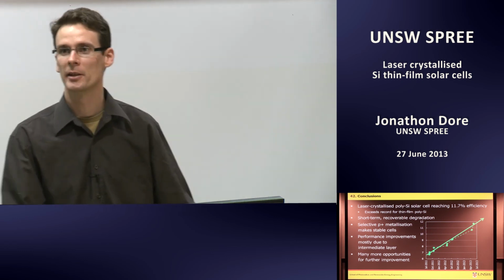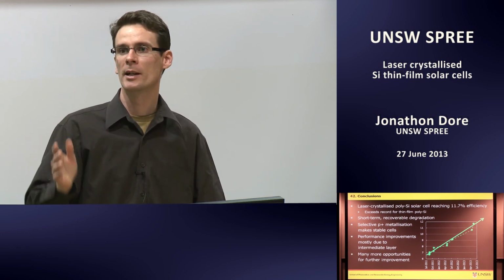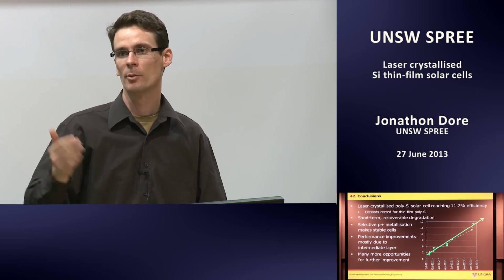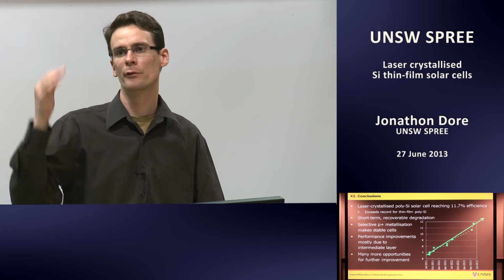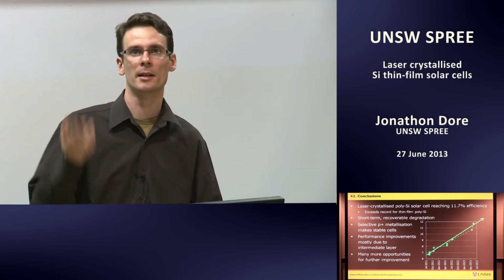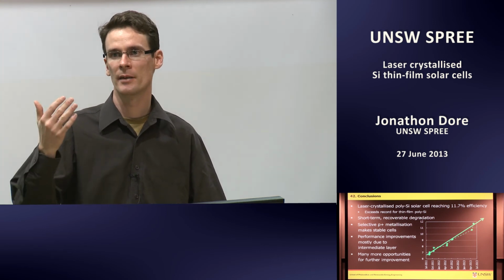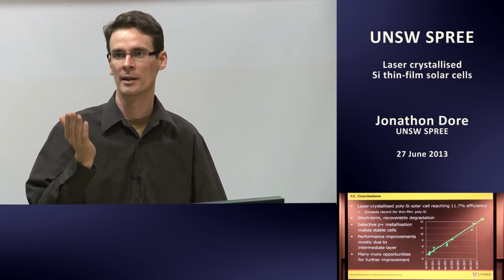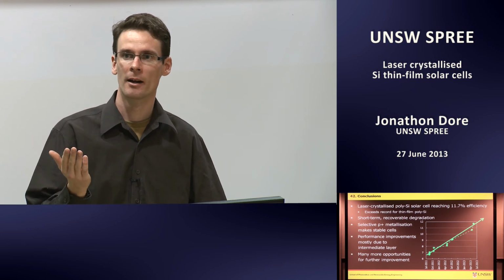Yeah, the short answer is neither do we. One thing I'll quickly point out is that it's not degrading the EQE. It's quite interesting that the EQE and IQE are staying stable. So when we look at the current overall, that's not being affected by this degradation. It's mostly in fill factor and voltage. Now, we understand that at lightly doped contacts with aluminium, we get a bit of a Schottky barrier there, and that's going to affect the voltage and the fill factor. But why it would change with baking and non-baking is not quite clear.